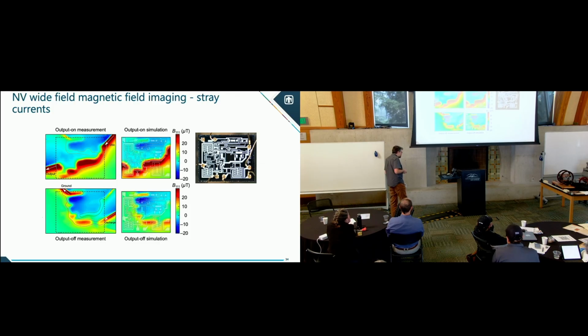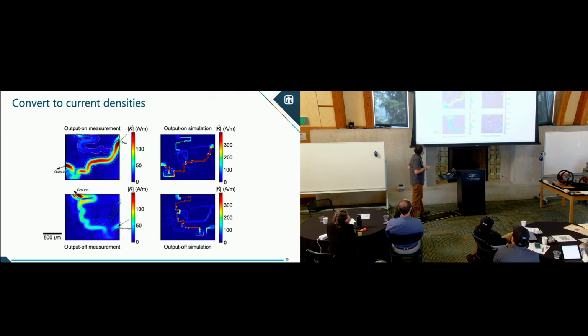In this case, we actually even put the diamond on top of the wire bonds for the device. So it's standing off by about 50 microns, which actually blurred the resolution a bit. But the point comes across. Now, this is just the magnetic fields. You can actually invert the Biot-Savart law on this and actually show where the current density is and the direction of it. So this is the current density.